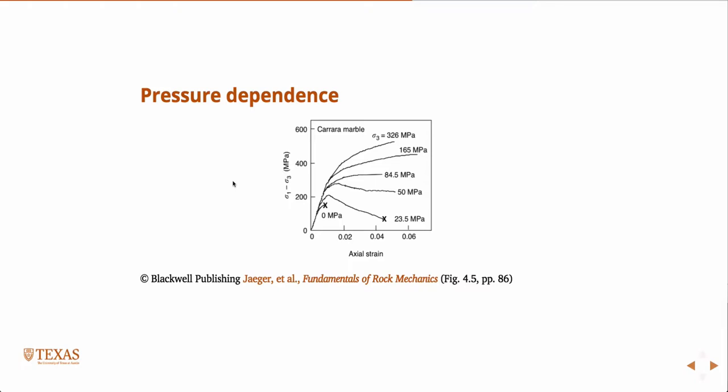Well, at very, very low confining pressure, you can fracture it quite easily, right? But 50 MPa is like a real in situ stress. So you don't fracture it at all. And it goes out to almost 6%, 5% strain. So it has quite a bit of what we'd call ductility, right? Which people don't really think of rocks as ductile.